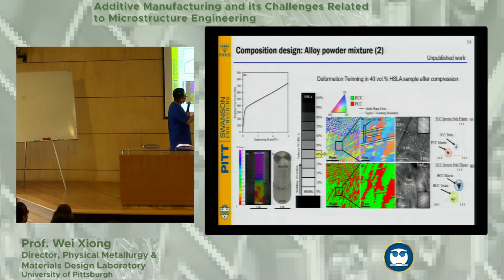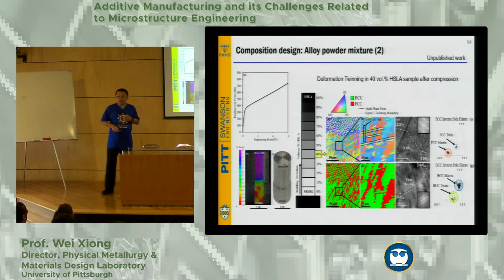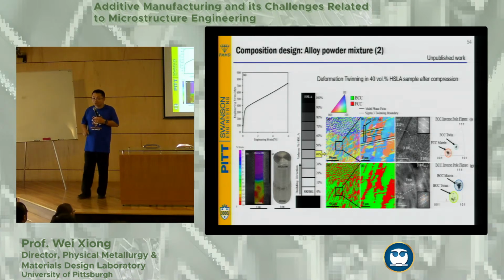This is 40%, and after deformation you can see the twin structure forms - you do see the twin structure. With 50%, we can also see the twin structure with martensitic transformation under deformation. That's actually TRIP and TWIP effects.